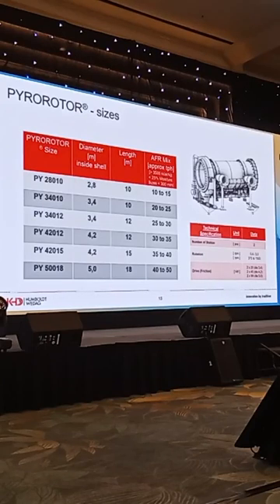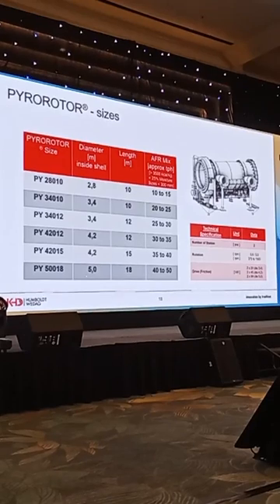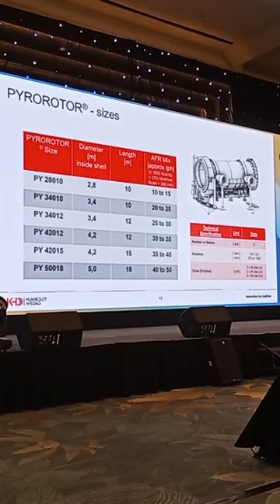So for the range below 3,000 tons, we have now also developed a smaller size with only 2.8 meters in diameter, and for kiln plant capacities over 8,000 tons, we have this 5-meter pyrorotor. You see the amount of alternative fuels which can be fed to such a system. In the standard range we are talking about an alternative fuel feeding capacity of nearly 500 tons per day, or even going up to 800, 900 tons per day. This amount of fuel also has to be handled in your plant. You have to think about the size of the storage and the pre-preparation. Okay, this is not necessary in this case with such an implementation of the pyrorotor.